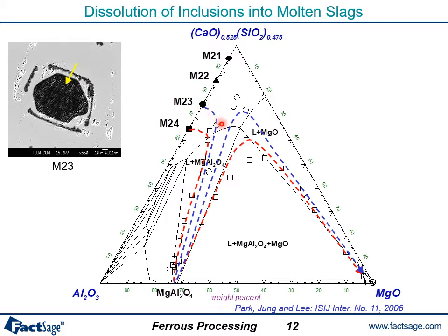So we go from here and this way, and this middle wall has the spinel composition, MgAl2O4. It goes here, here, and then the inner side liquid actually has the co-saturated slag composition of MgAl2O4 and MgO. So the slag is co-saturated. Then it goes here, here, back to the inner liquid, and then to the MgO particle. This phenomenon is very interesting, but if you look at the actual phase diagram, you can understand this very quickly.